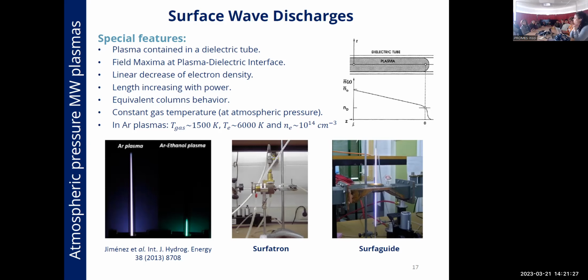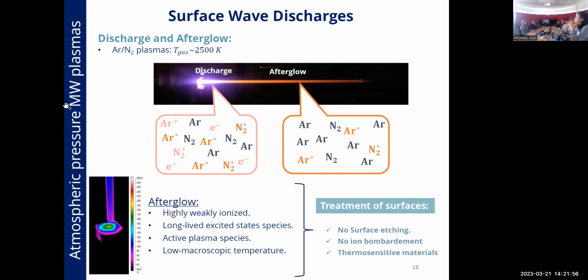What kind of applications are we doing with this plasma? We are producing hydrogen, also graphene and multi-wall carbon nanotubes, and doing surface modification and applications for food preservation. Actually, one feature really interesting and important for our applications is that, working in specific flow conditions, for example with argon and argon-nitrogen, under certain conditions it is possible to have what is called afterglow or plasma post-discharge. Here in the slide, you can see that the discharge is the brightest part, whereas the afterglow is the more diffuse area.